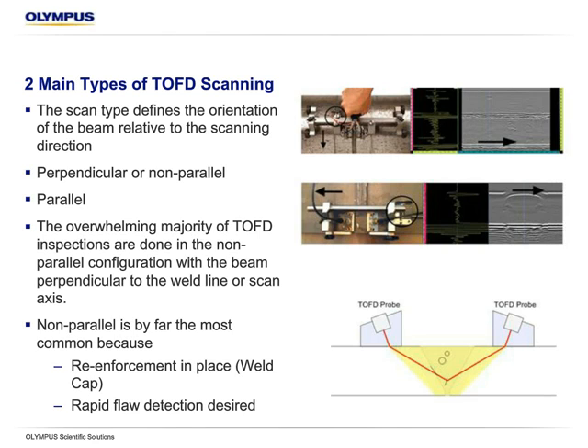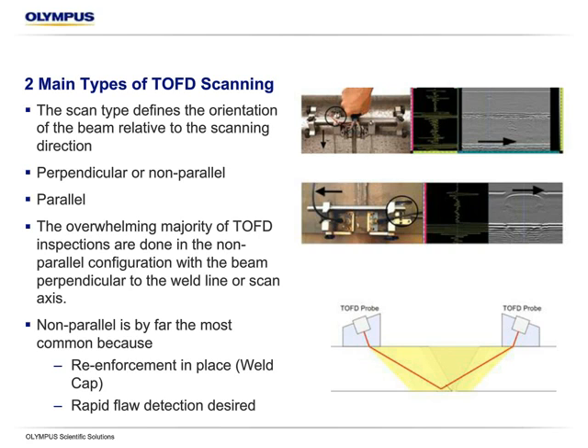So if you want to get that index position with a perpendicular scan, the easiest thing to do is go back with a pulse echo probe and just get the exact index positioning that way. So by far, because a lot of welds have reinforcement in place, and also because we want to do a very rapid scan, most TOF scanning is done in the perpendicular or non-parallel fashion. You can see a little differences there between the two.